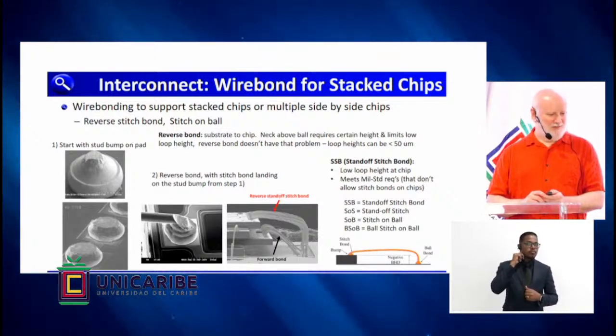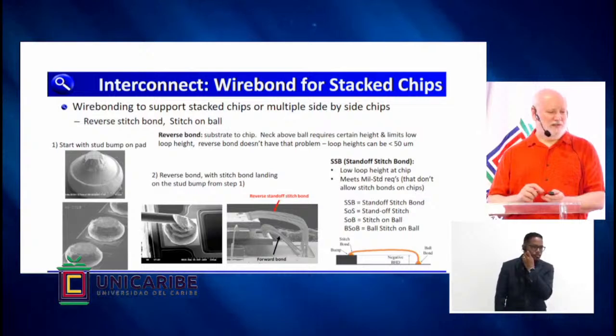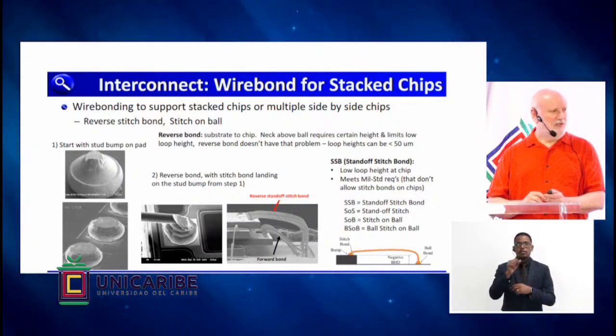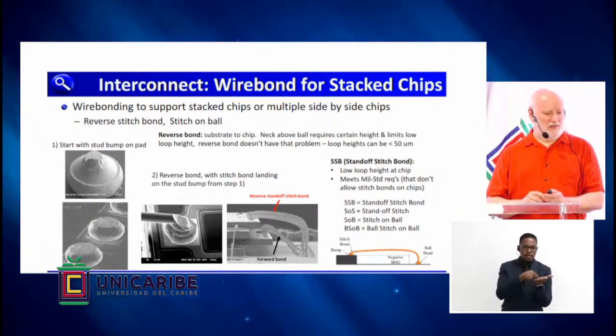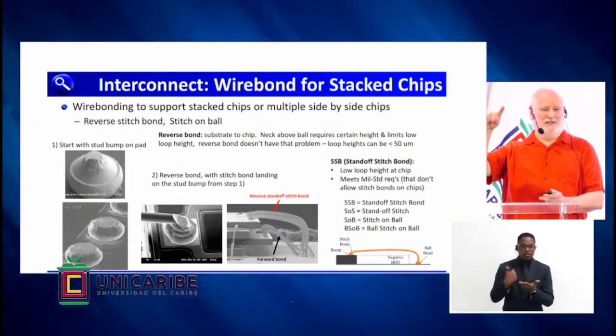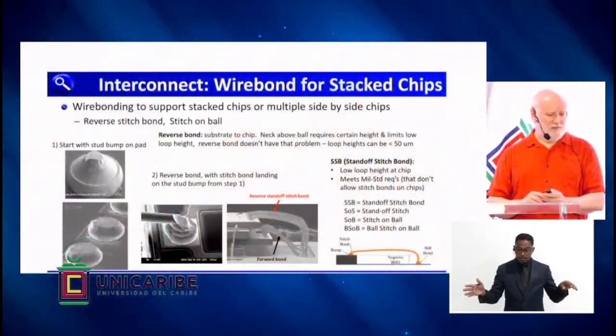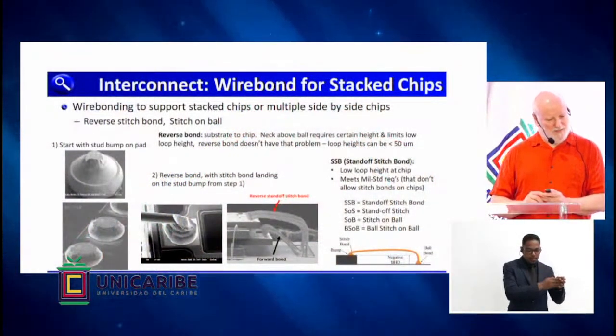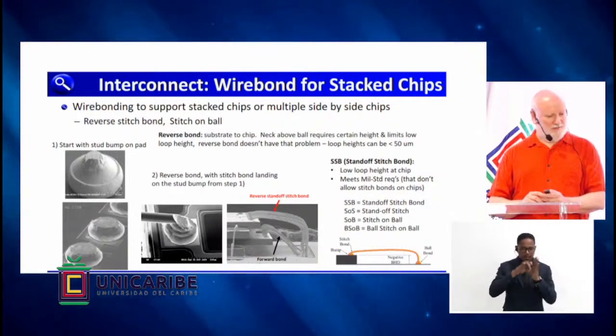When we talk about stacking chips and the desire to keep the overall stack very thin, that becomes a problem with wire bonding, because with wire bonding typically the loop comes up before it goes down. So what has been developed is something we call a reverse stitch bond. Essentially you put down the ball part of the bond on a bond pad first, and then instead of bonding from the bond pad to the substrate, we reverse it. We bond from the substrate to the chip bond pad, but on top of that ball that has been previously placed. So that's what you see in the lower image on the right, where it's labeled reverse standoff stitch bond.